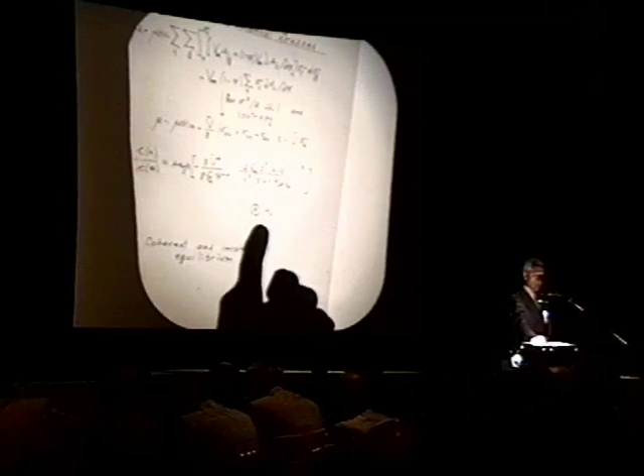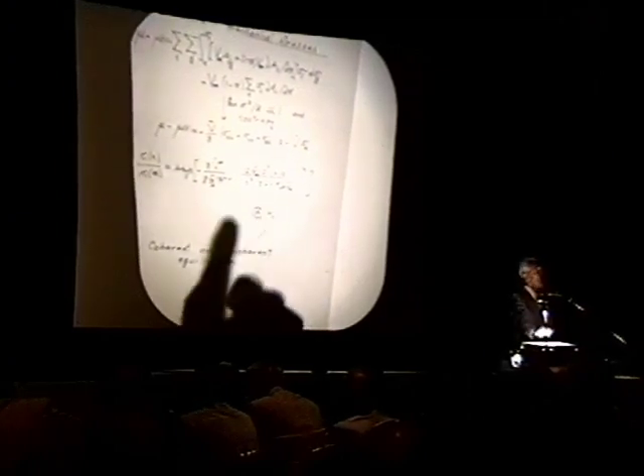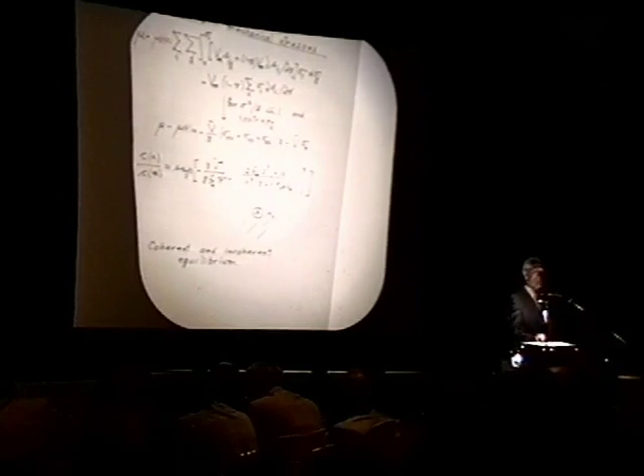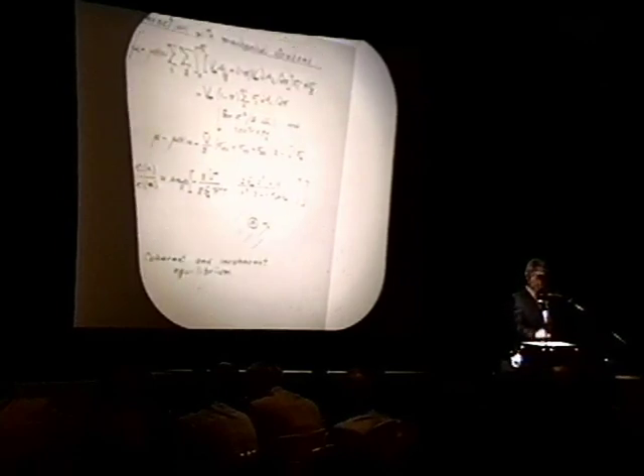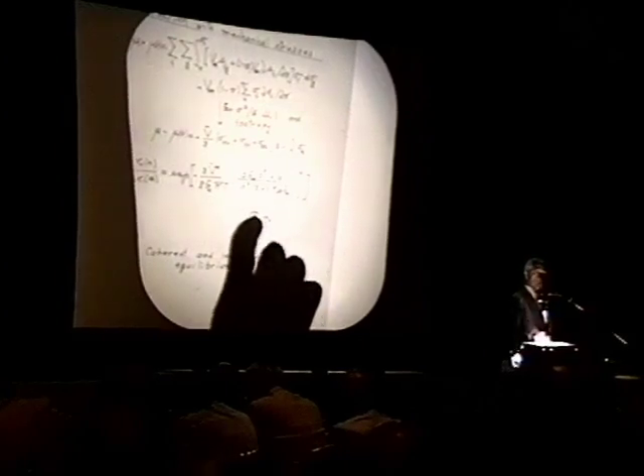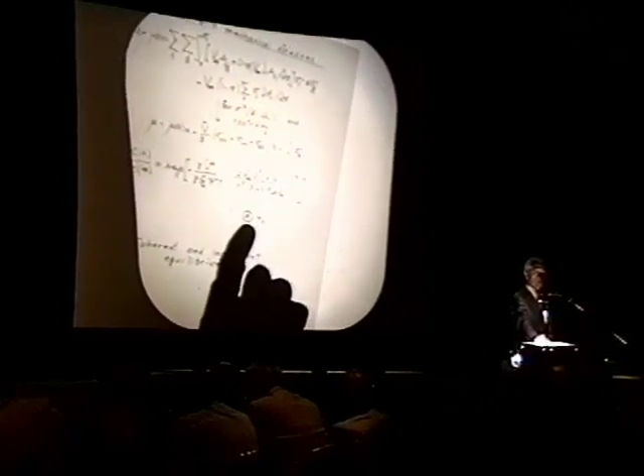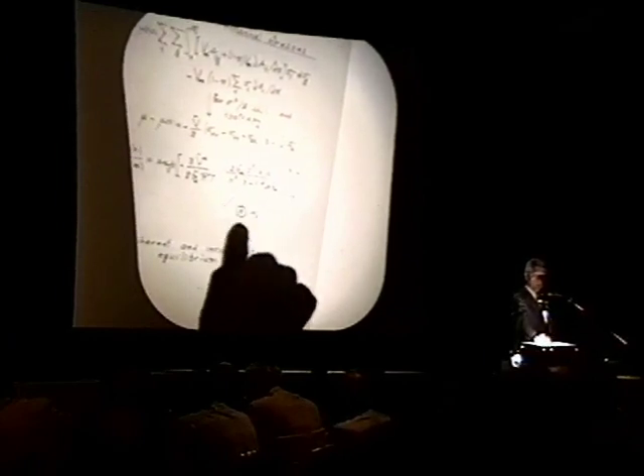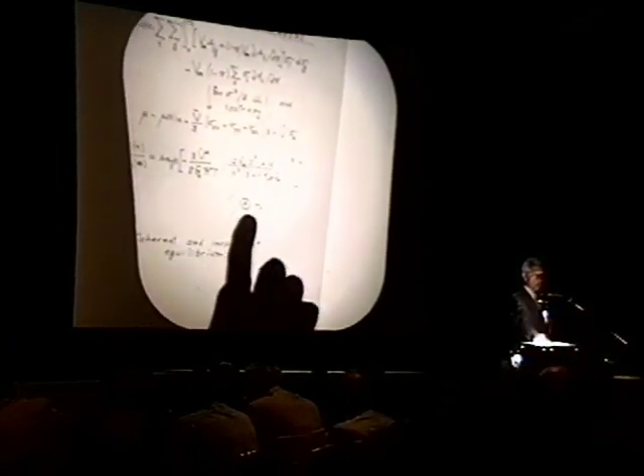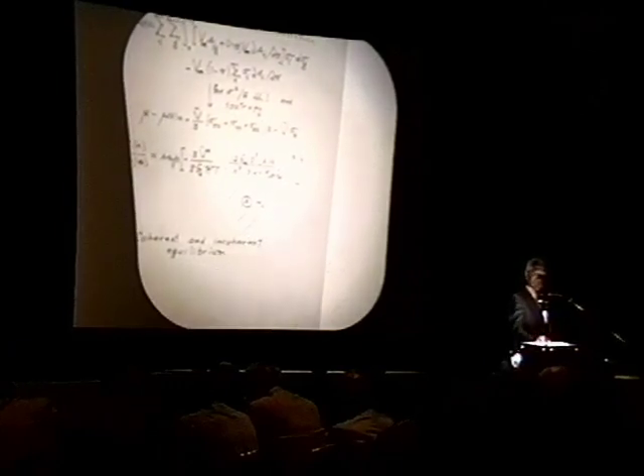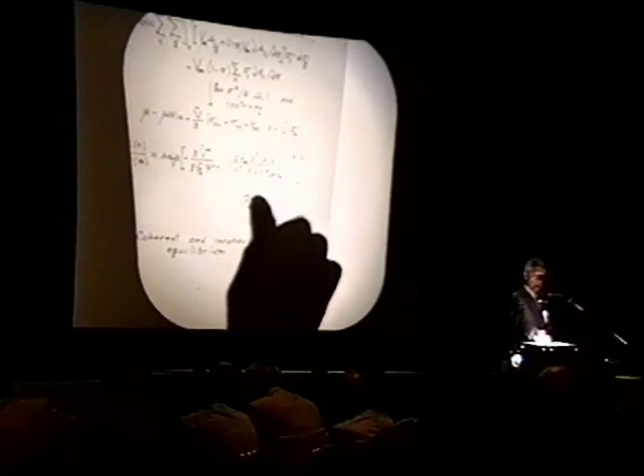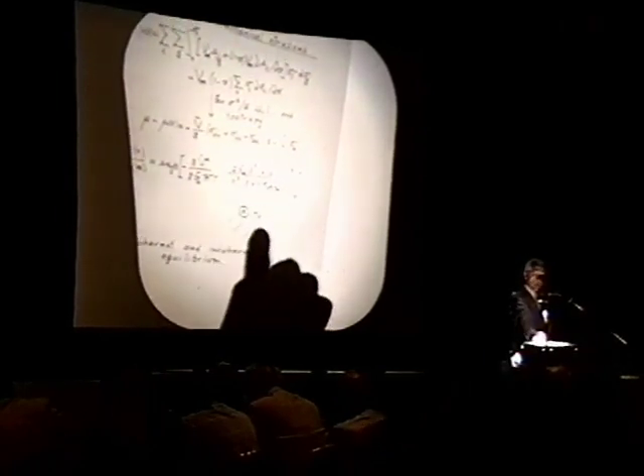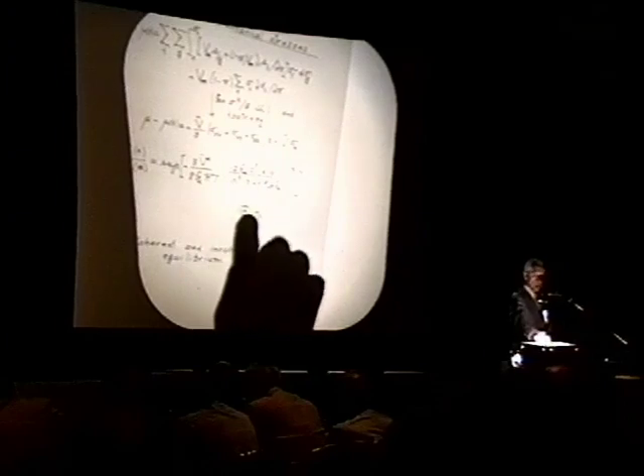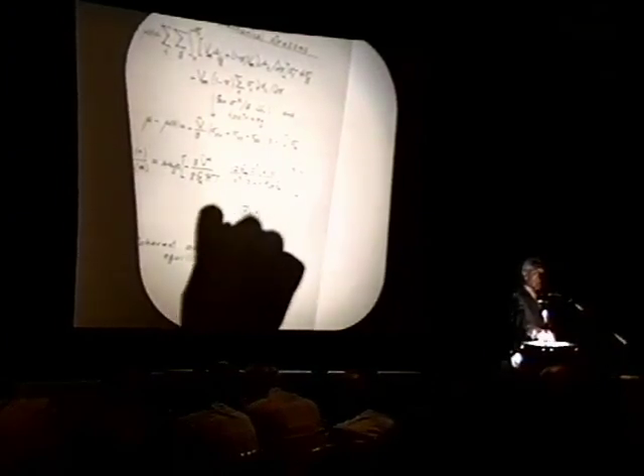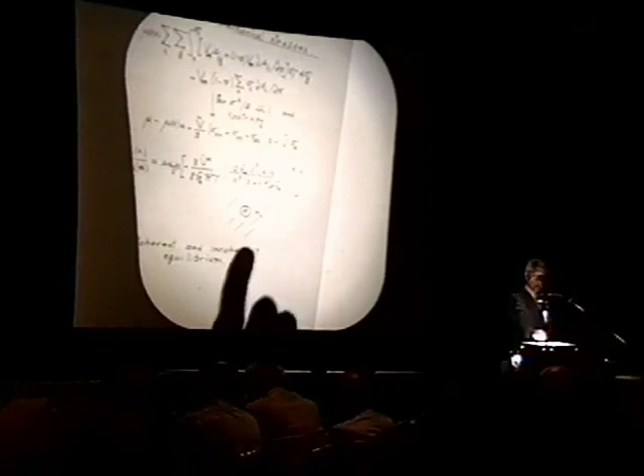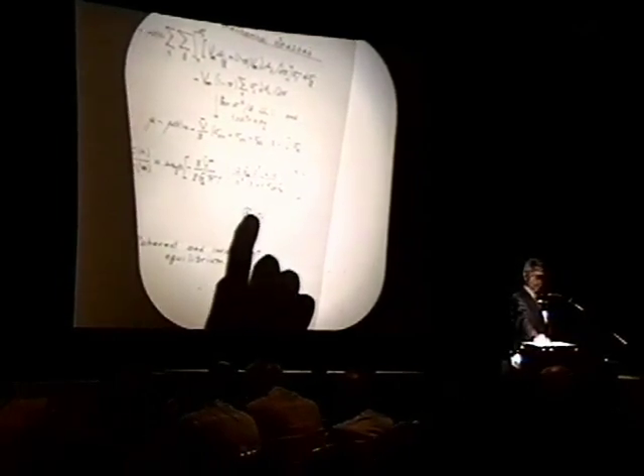The consequence of that is that, because in the beta phase the partial molar volume of the hydrogen, although it's somewhat smaller, there's more hydrogen here than in here. This is a larger volume than the cavity which gave rise to it. As a result, this really exemplifies that elastic model that I showed you earlier, and one has effectively a compressive force upon the beta. And out here, to a first approximation, this is spherical, one has zero hydrostatic component of stress. So that its concentration is therefore increased.